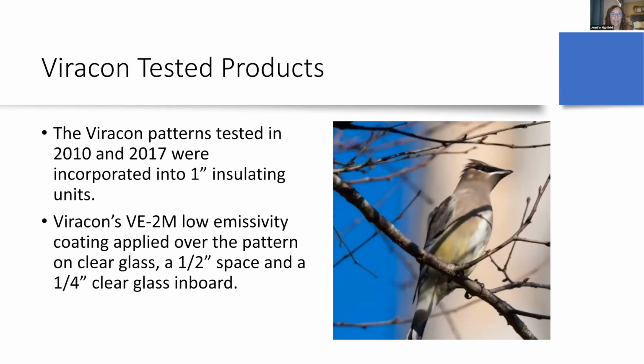The Viracon patterns tested in 2010 and 2017 were incorporated into 1-inch insulated units. The outboard glass ply was a 1/4-inch clear glass with a ceramic enamel, frit or ink pattern on the second surface, and then Viracon's VE2M low-E coating applied over the pattern on clear glass with a 1/2-inch airspace and a 1/4-inch clear glass inboard.